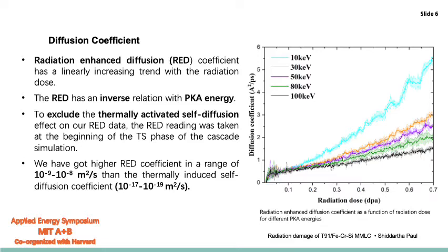To exclude the thermally activated diffusion coefficient, we recorded the radiation enhanced diffusion coefficient at the very beginning of the thermal spike region, and we got the radiation induced diffusion coefficient in a range of 10 to the power minus 9 to 10 to the power minus 8 meter square per second, which is actually higher than the thermal diffusion coefficient. We can also see the radiation induced diffusion coefficient decreases as the primary knock-on atom energy increases. So they have a pretty much inverse relationship in this case.